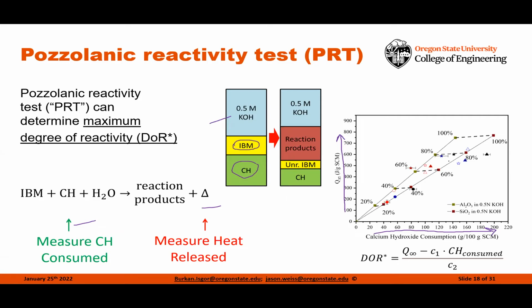And what we can actually do is, for a pure silica system, plot out these reactions from 20% reactivity all the way up to 100% reactivity. We can do the exact same thing for alumina here. And essentially now, if we start to plot some of these SCMs that we're testing, we can tell you exactly how much of that system is reacting. So this may be a fly ash with 20% reactivity. This may be a silica fume that's almost 80% reactive in the system.